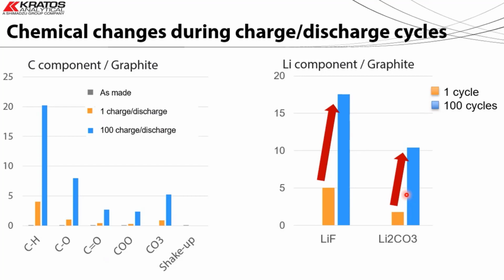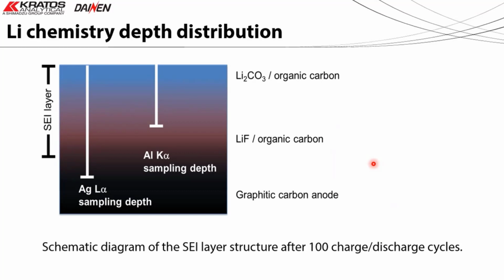And that's allowed us to conclude that because we're seeing this increase, we're looking deeper. This lithium fluoride layer must be sitting below the lithium carbonate in the SEI. So we are seeing a concentration gradient through the SEI layer. This is a schematic diagram where we've got a higher concentration of the carbonate species towards the surface of the material. The lithium fluoride degradation product, or what becomes the SEI layer, is much closer to the graphitic carbon